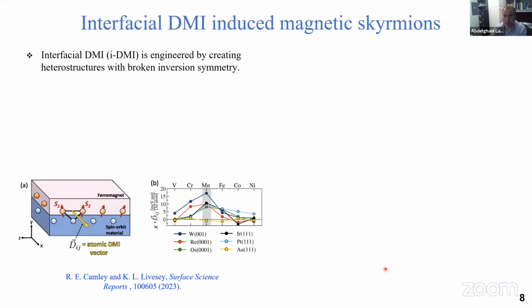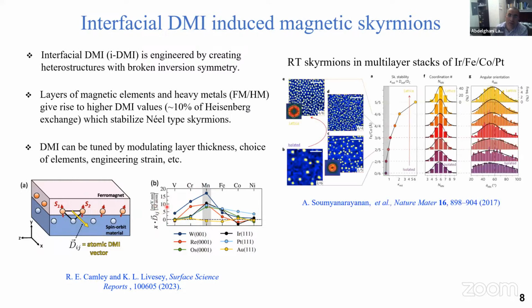Another kind of DMI is referred to as interfacial DMI. Usually you can engineer it by making heterostructures of ferromagnetic and heavy metal layers. This breaks the inversion symmetry. For example, by choosing the heavy metal, you can increase the DMI strength. This DMI can be really high, up to 10% of the Heisenberg exchange, and in this case it stabilizes Néel skyrmions.